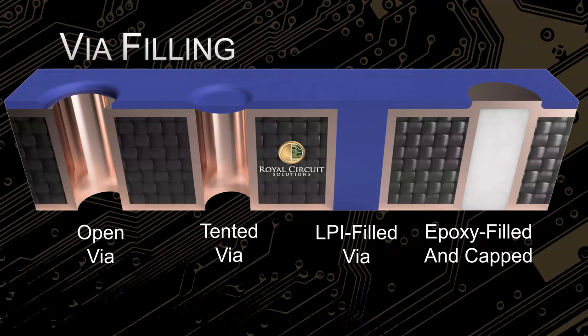So we talked a little bit about via filling, and some of the reasons that you would use this from a designer standpoint. Really, it happens on the assembly side, right? If you have, say, a thermal pad with a bunch of vias going through connecting to your ground plane, those barrels are just going to suck all of the liquid solder metal right out once it liquefies in the reflow process. It's just going to suck into those joints, and you're going to be out of luck when it comes to assembly. Your part isn't going to have enough solder to hold it down, or it's going to have poor thermal conductivity because with the solder down in the hole, you're going to have air between your IC and your land pad. So that's no good.